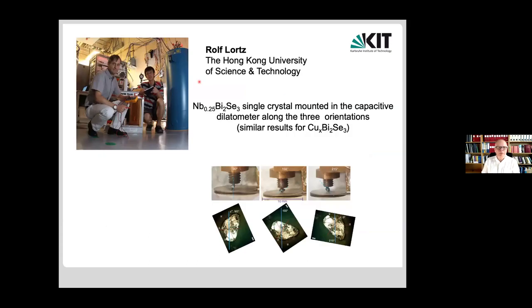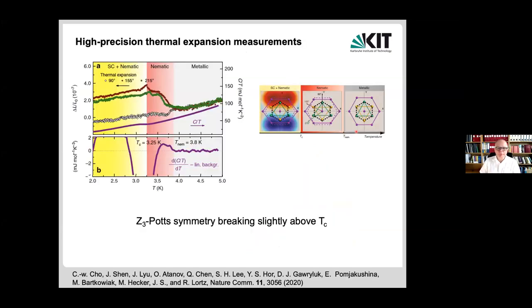When I presented those ideas a while ago, probably 2 years ago, at a meeting in Beijing, Rolf Lortz approached me because he had been doing experiments on niobium-doped bismuth selenide, where he looked at thermal expansion for three different crystalline orientations in the system and found something quite intriguing. In the meantime, there are similar results also for different compositions, so this might well be something generic. So what does he find?